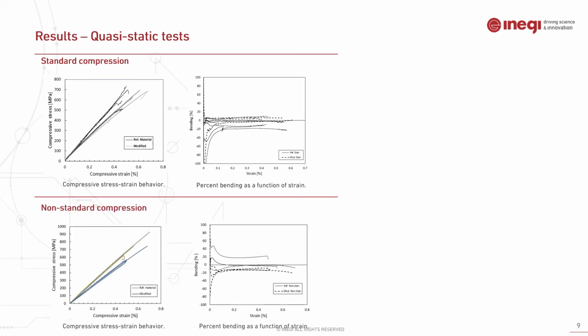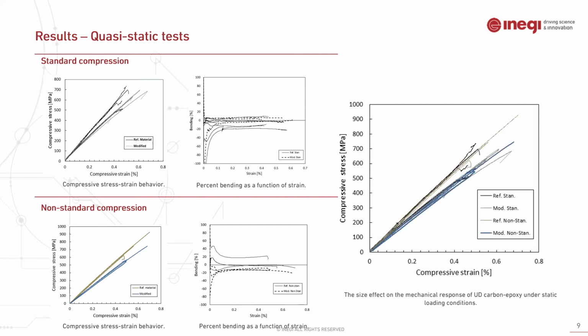And in the case of the non-standard compression test using the fixture compatible with the Hopkinson bar, we have the same type of behavior for both material configurations. Again, we can see a notable decline in the stiffness values of the modified specimens, while we can also see a 20% decline in the ultimate strengths of the modified specimens. And over here on the right again, we have percent bending as a function of strain, showing a deviation ranging between plus or minus 20%. And finally, we have the overall comparison between the two test fixtures, showing the reliability of this new fixture.